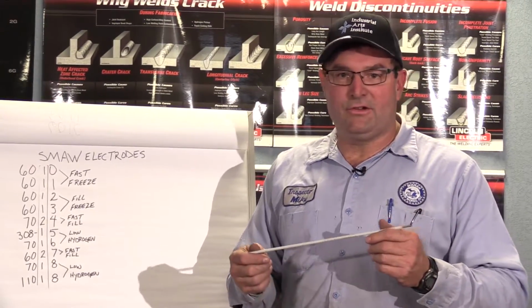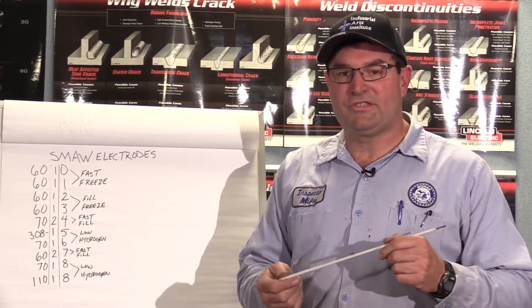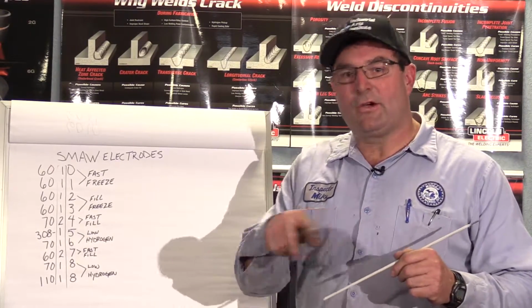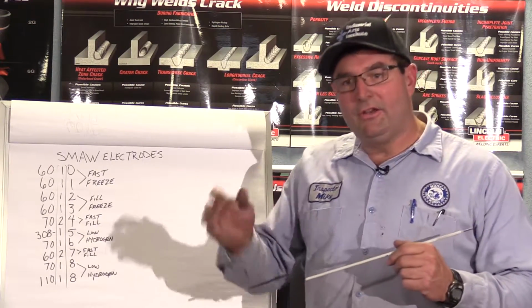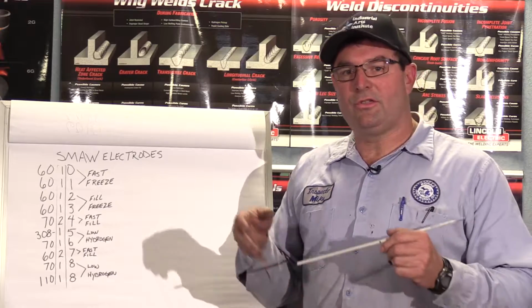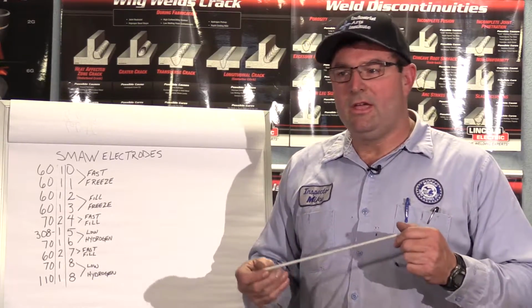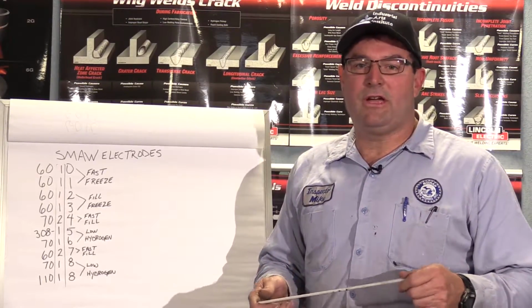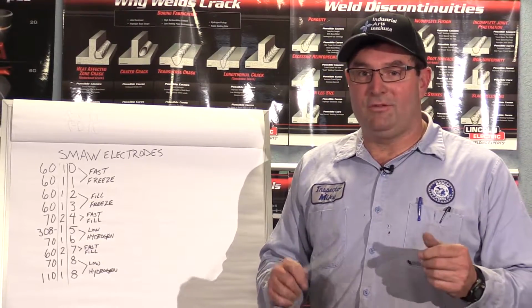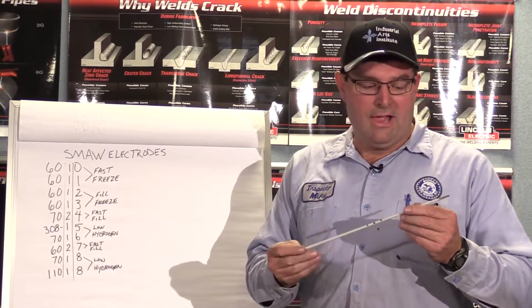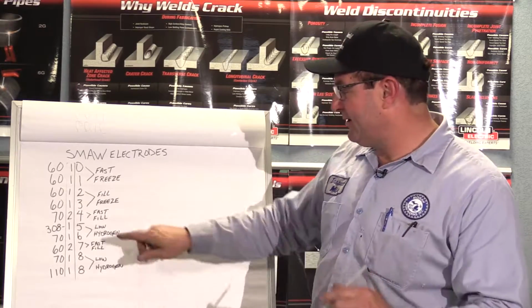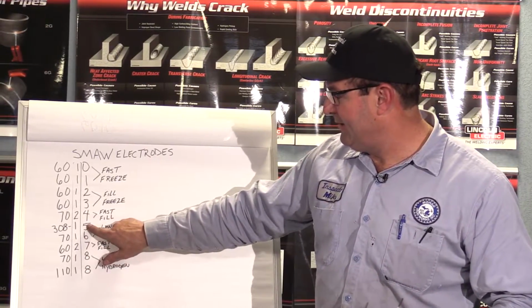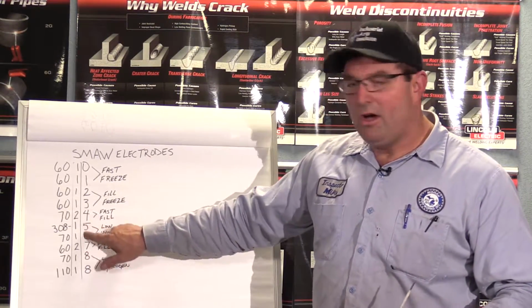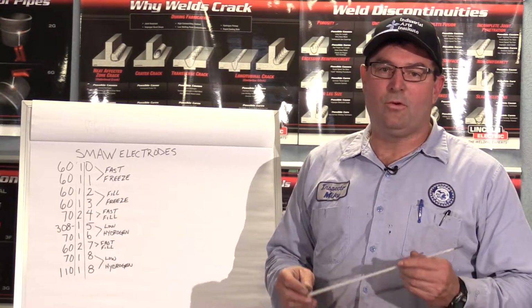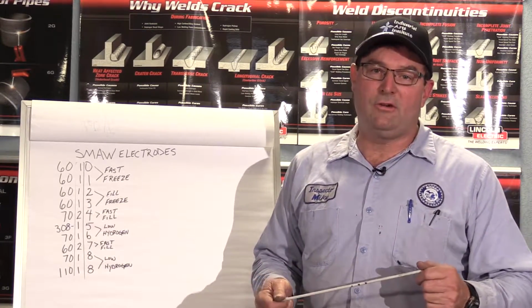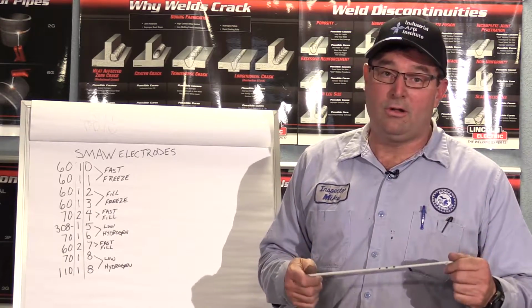Hydrogen cracking is not what you're going to see on the surface. You're not going to weld with this type of electrode and then look at it and see cracks. Not where they're at. They're in the underbed. The thicker the material, the more likely you would have this issue. You could counter hydrogen cracking by preheat, and the best thing is using the proper electrode. These type electrodes, all of these low hydrogen, 15, 16, and 18, should always be kept in a sealed container away from moisture, or better yet in a rod oven at 250 degrees or more.